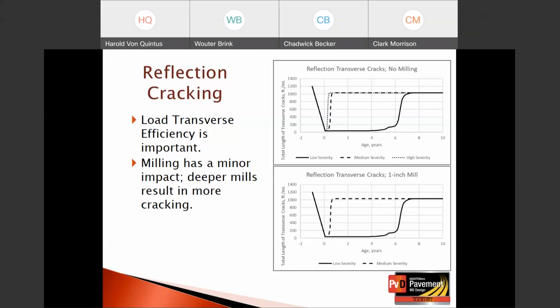The graph on the bottom is the same thing, but for only low and medium crack severity with a 1-inch mill. And the milling depth basically has a minimum impact on the predicted transverse cracks.